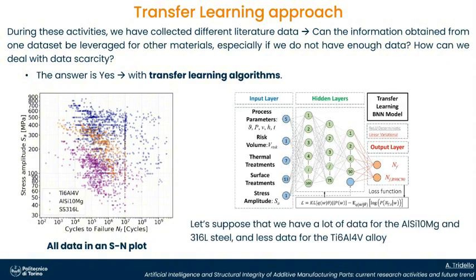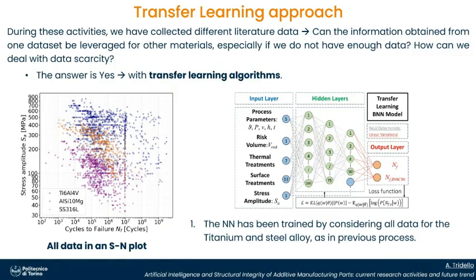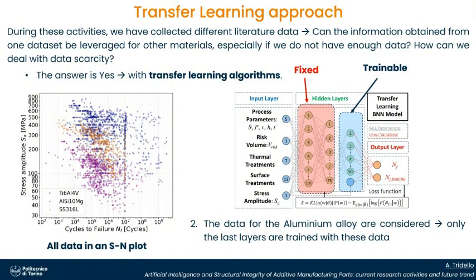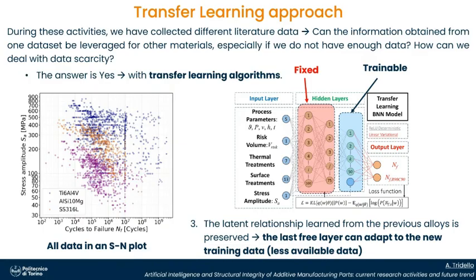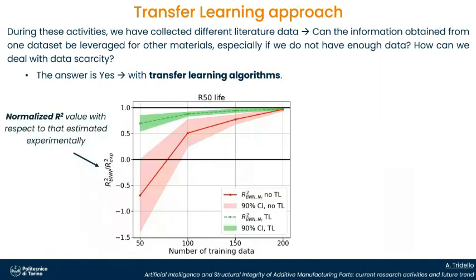Let's suppose that we have a lot of data for the aluminum and 316 steel and less data for the titanium alloy. The neural network has been trained by considering all data for the titanium and steel alloy, as in the previous case. This is quite common. After that we consider data for the aluminum alloy, but only the last layers are trainable, and are trained with the aluminum alloy. In this way, the latent relationship learned from the previous alloy is preserved, and the last layer, which is free, can adapt to the new training data for which we have less data. So we can try to exploit the relationship learned from other data sets for which we have more data.